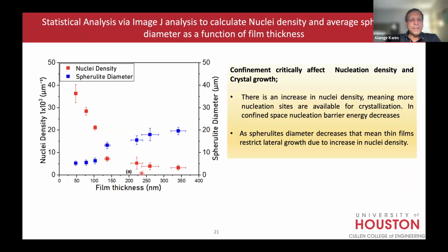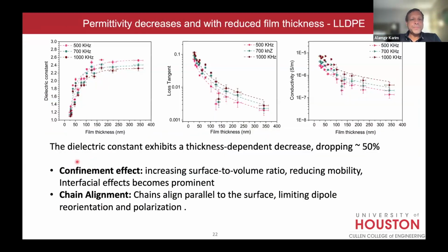So they make very many nuclei. And because they make many nuclei and these grow and they impinge on each other, they can only grow that much. So the spheroid ultimate diameter before they impinge on each other is very small. In thick film, the nucleation density is lower, but the spheroids can therefore grow to larger dimensions and then impinge on each other. But somehow, this combination of high nucleation density with low spheroid diameter is giving us the high breakdown strength. As I said, we see it also in glassy, so I'm not sure it is related to crystallinity or not, which is interesting.